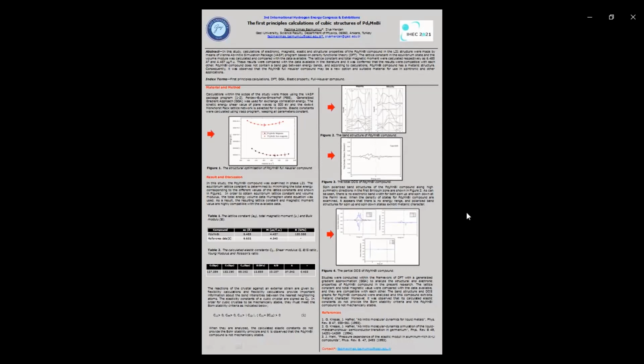The spin polarized band structure of this compound along high symmetry directions in the first Brillouin zone is shown in Figure 2. As can be seen, there is no electronic band gap for both spin up and spin down at the Fermi level. When the DOS graphs for this compound are examined, it appears that there is no energy gap, and the polarized band structure for spin up and spin down states exhibits metallic character.